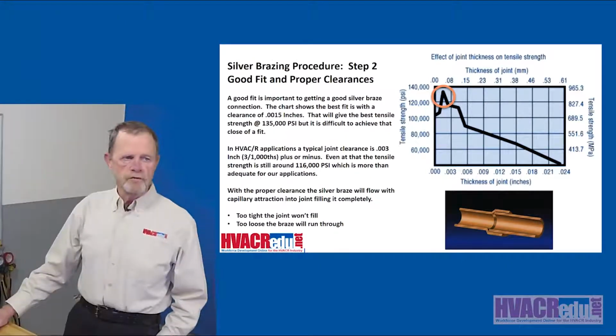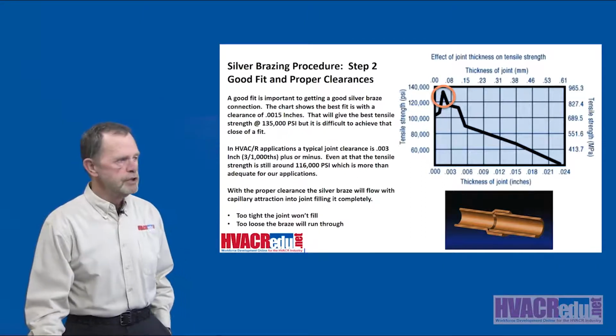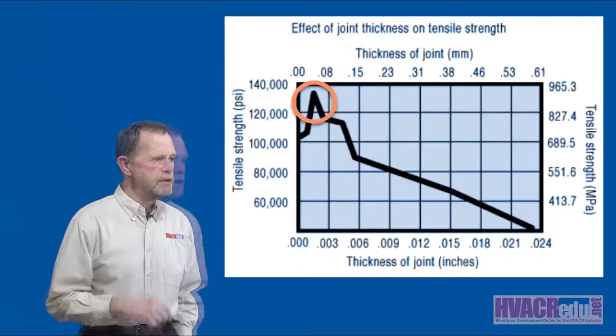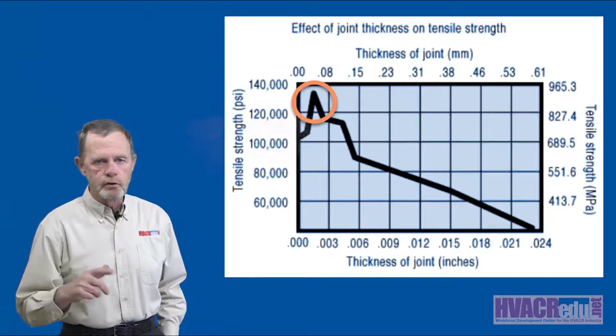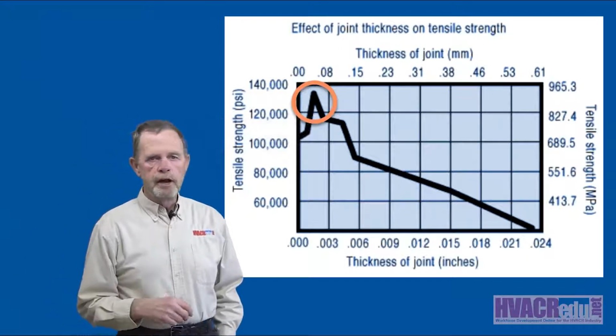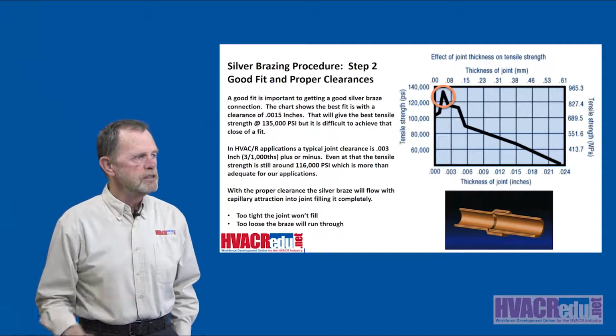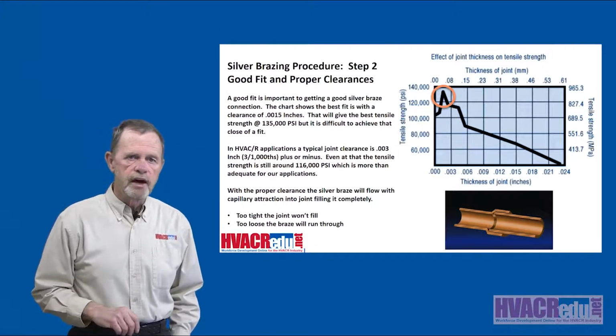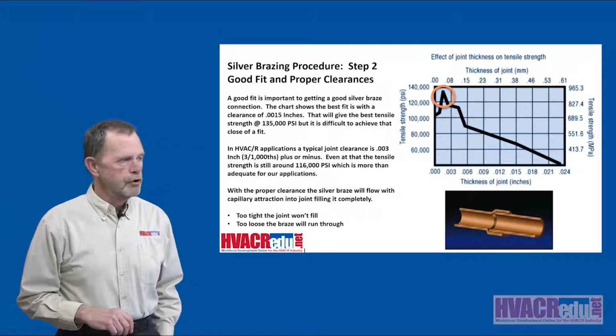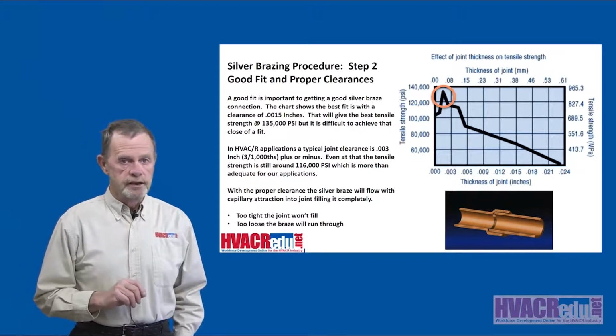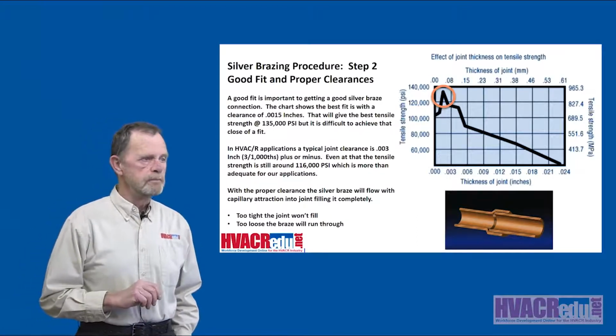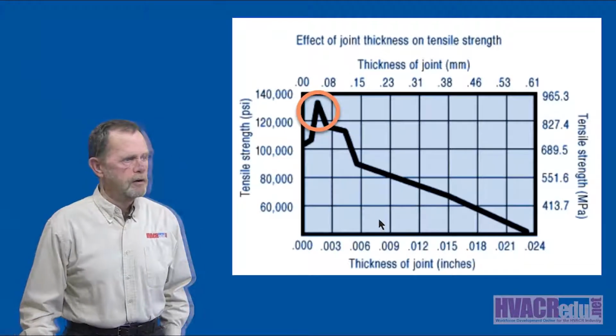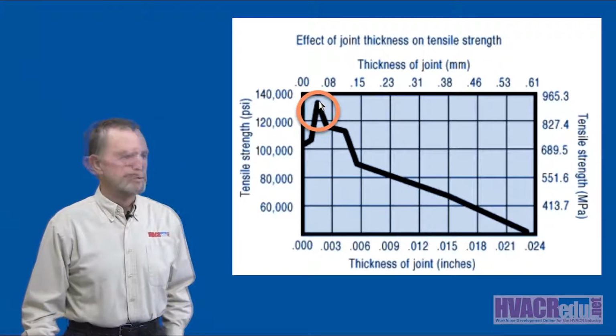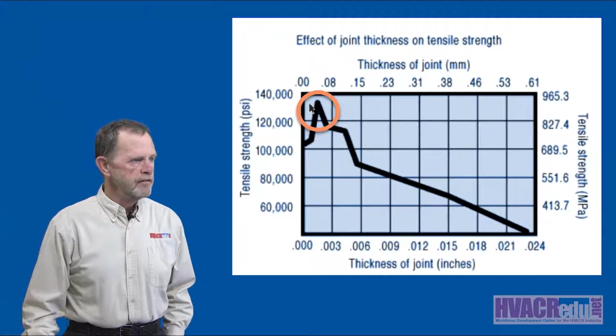Yeah, good fit is important to getting a good silver braze connection. The chart shows the best fit is with a clearance of 0.0015 inches. That would be 1.5 thousandths. That will give the best tensile strength, that 135,000 psi that I mentioned earlier. But it is difficult, it is, to achieve that type of fit. And you can see the chart here. Here's my peak best fit situation, and then it gives me 135,000 psi tensile strength.